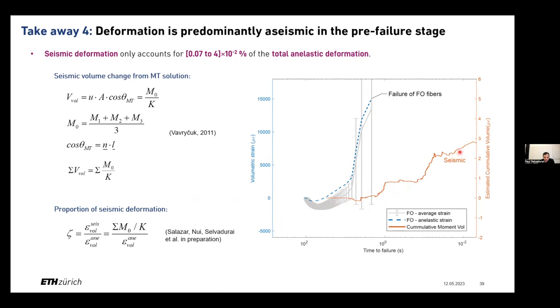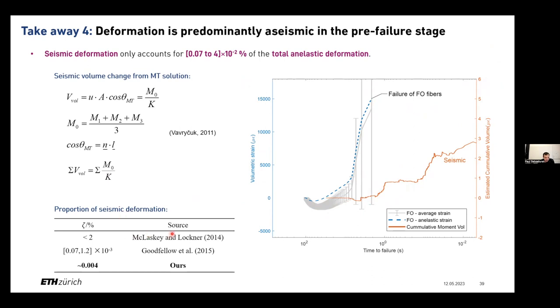But when we look at even the worst case, we're looking at a very small percentage of the volume change here that is seismic, where a majority of the deformation appears to be aseismic. And this is consistent with other laboratory studies and also what people are seeing in natural conditions. So we had around 0.004% of deformation emitted seismically.